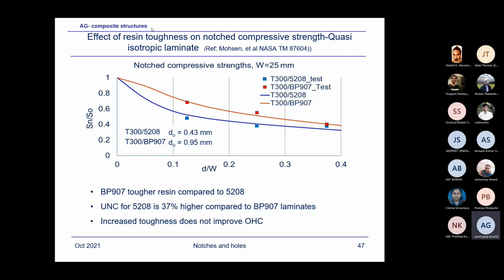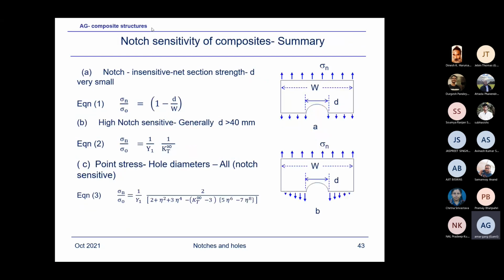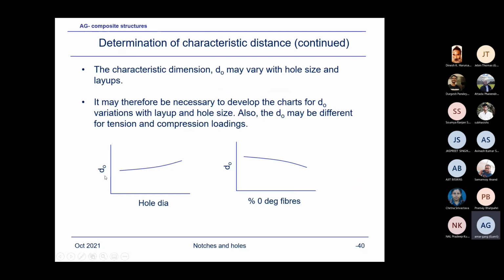Suppose in the design office, we are working and we want to predict the notch strength, the hole strength. We would have generated by test data various charts. As I said earlier, normally we'll develop charts like D naught versus hole diameter for a particular material, and also as a percentage of 0-degree fibers for various layups. And that should be good enough. Once we have for that material these variations, then you can apply that for the same material with the relevant diameter and percentage 0-degree fibers. So you've already calibrated your D naught for particular material. Yes, sir. So these are calibrated graphs.